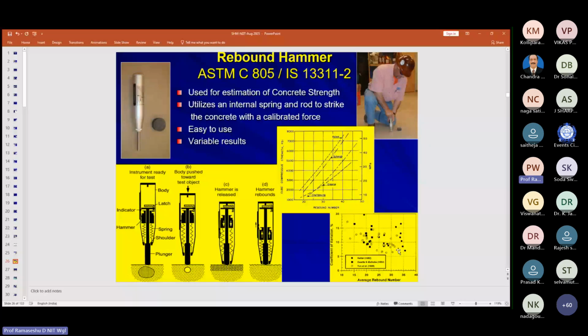But there is a small problem. Whenever the plunger happens to be on an aggregate very near the surface, it definitely gives a higher rebound number, which may lead to misleading results. That's why you should take a number of points, take these rebound numbers, and then take the average. Sometimes carbonation makes the concrete surface harder. Carbonated concrete is much harder, so a carbonated surface also gives a higher strength.